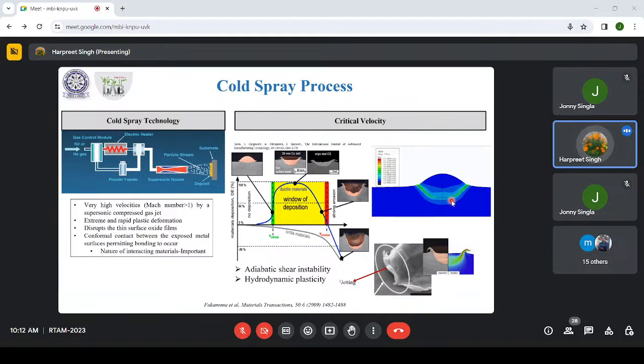Now, what is happening is that at the interface, the temperature is so high that there is localized melting, according to one of the theories which is widely accepted. This localized melting is what makes the bond even stronger, right? Of course, deformation is helping us, but this localized thing too. Since the temperature becomes very high, reaching the melting temperature, you will expect that the shear stress of this material will fall to zero. And when it goes to zero, there will be very easy flow at the interface, and you will get this kind of jetting outside.